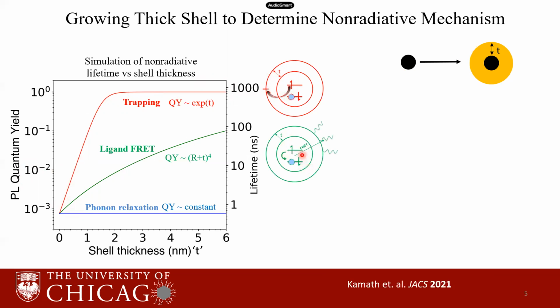The ligand FRET is an electromagnetic coupling between the quantum dot state and the vibrations on the surface. So as we grow this shell, we should expect the PL quantum yield to increase as a fourth power of the total nanoparticle radius. Since phonon relaxation is intrinsic to the core material, the growth of the shell should not have any effect, and we should expect the quantum yield to be independent of the shell thickness.